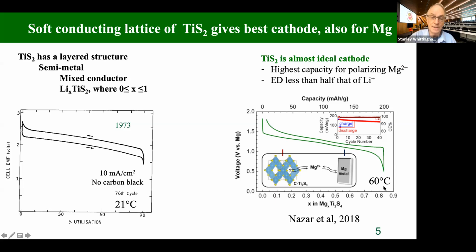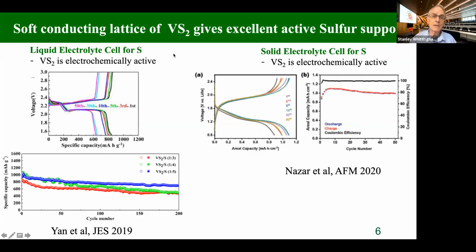And you'll notice it's also run at 60 degrees centigrade compared with the 21 for the titanium disulfide. Other folks are now looking at calcium diffusing in this material. So again, this soft covalent lattice lets a lot of ions diffuse much more readily. It's also been studied lately as an electrochemically active substrate in lithium sulfur batteries. In the examples I show you here, this is vanadium disulfide, essentially the same structure. On the left-hand side, this is a non-aqueous electrolyte. And you can see getting over 800 milliamp hours per gram, very high values here, and not too much polarization.